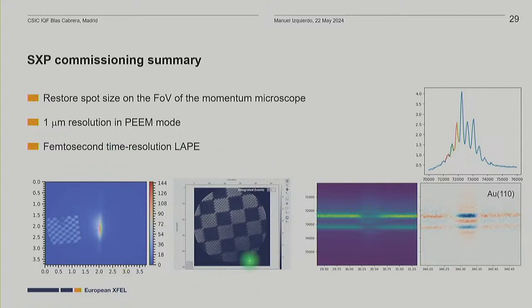In PEEM mode, we can resolve 1 micron structure, so the typical resolution in PEEM mode is around 500 nanometers, which is worse than a dedicated PEEM system, but still allows us to do experiments with submicron resolution.